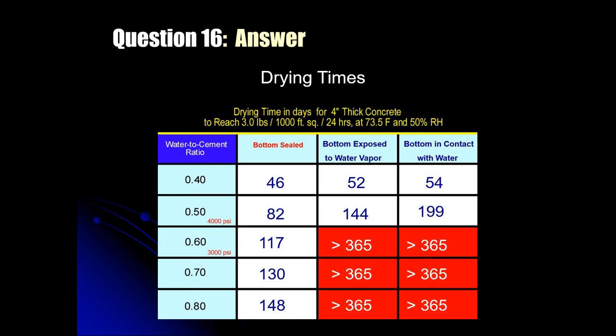The old adage: damp clothes on a damp day don't dry. So there are parts of this country at certain times of the year where it's virtually impossible to get a slab to dry naturally to an acceptable level. Now, there are areas like Nevada and Denver that have extremely low relative humidity, where if the slab surface were open enough to freely release its moisture, you've got half a chance if you've got a very prolonged construction schedule. But it's not going to happen in 2 or 3 months.